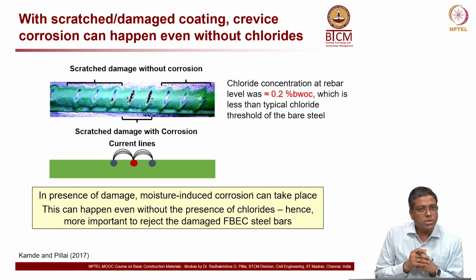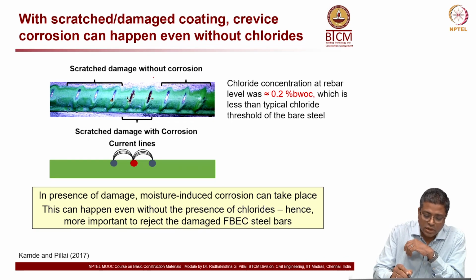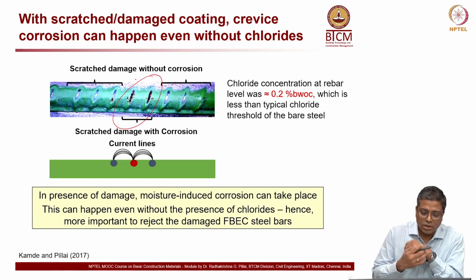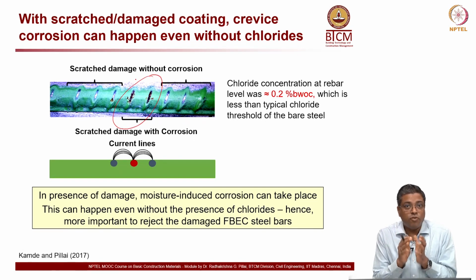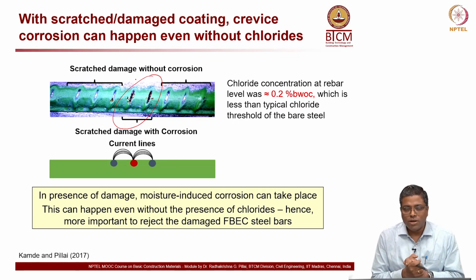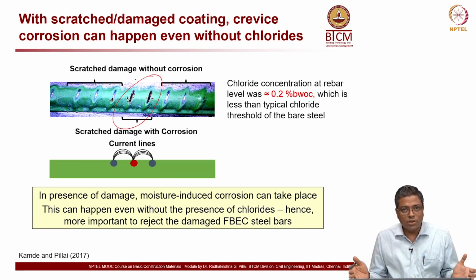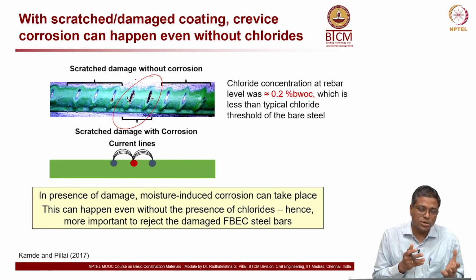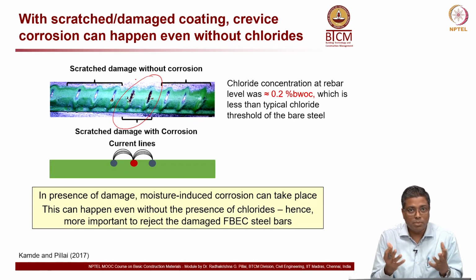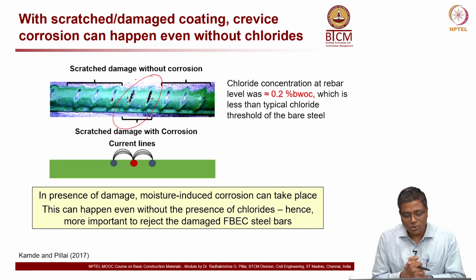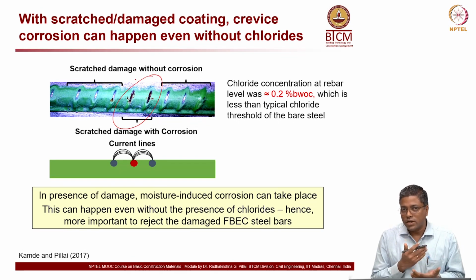And so, what is the corrosion mechanism? How do they corrode? This is from some experiments which we did in our lab, by Dr. Deepak Kamde. You can see that some of the scratches become anode, whereas the other scratches become cathode. In a corrosion reaction there is an anode and a cathode, like in a battery. The anode is the location where it corrodes, and the cathodes are the locations on the bar which help it to corrode.